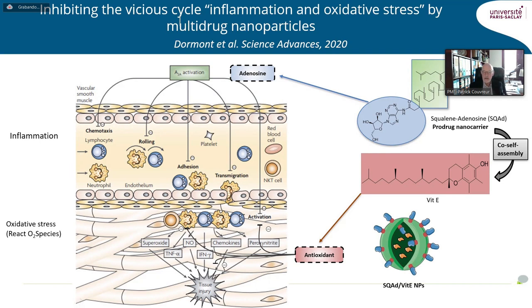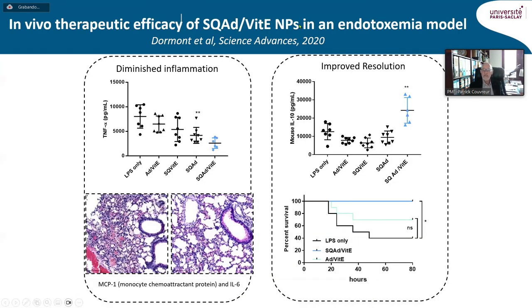And we have tried to inhibit this vicious cycle between inflammation and oxidative stress by the design of multi-drug nanoparticles, which will combine, from one side, adenosine through adenosine squalene, because adenosine can interact with the adenosine A2A receptors, as you can see here, which induces an anti-inflammatory process. And it is very easy to dissolve vitamin E into the lipophilic core of those nanoparticles, which will act as an antioxidant fighting against the oxidative stress. And you can see that on an endotoxemia model, this allowed us to decrease the inflammation process dramatically.